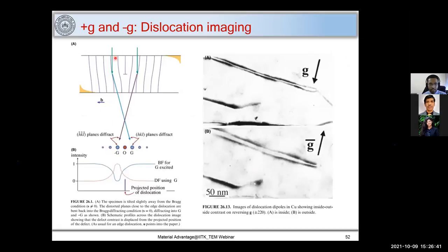We have seen this image already, and we have seen that the core of a dislocation gives you minus G and plus G. Now, if you use this spot to image the dislocation, you can see that the dislocations are narrower. If you use this minus G spot, you can see that the dislocations are wider here. So really, what you are doing is using strains, you are mapping strains. You are not actually mapping dislocations. You are mapping strains around these dislocations. That is why we get these differences when you use G or minus G to image dislocations.